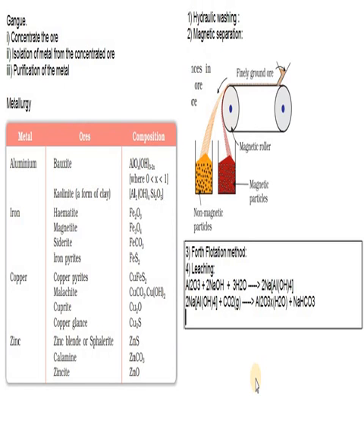So that's how you get a pure hydrated alumina. Now upon heating at 1470 Kelvin, the water of crystallization evaporates off, and then you get a proper pure alumina in a solid state.